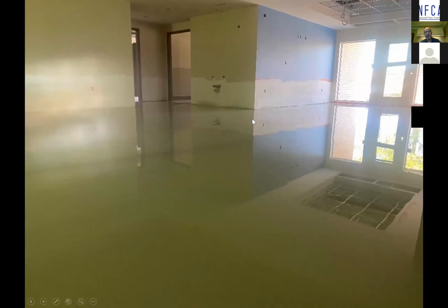So, for example, here's one, and this is a gypsum topping that is put down at 1/8 of an inch over a gypsum pour, and a water-based primer was used here, and you have a perfect canvas to install floor coverings on that is very high compressive strength and is super flat and super smooth for floor covering installation. And you can pour this in a fraction of the time if you need it.